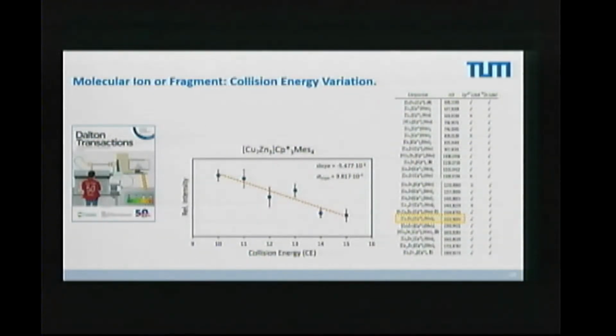This is not so different from what people do when they do cluster science in the gas phase. Imagine you have, let's say, a copper zinc aggregate of 20 atoms. You make it by evaporation of brass alloy, and you analyze what is flying around in your mass spectrometer as naked clusters. It's on the femtomole level, and they can do photoelectron spectroscopy with that or some other spectroscopies, and they get some spectroscopic traces. They have the spectroscopic information, and then they model it by guessing the structure. So this is kind of an iterative process. What we do is very similar to what they do. The complexity is higher because we have the ligands.